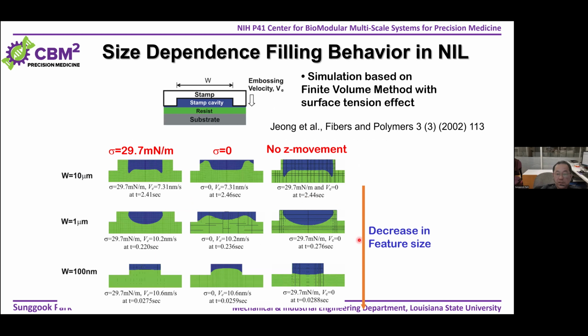And this is an older simulation result. What they want to show is how the polymer fills by squeeze flow in nanoimprint lithography depends on the surface tension as well as the size of the structures. When the size is large, the thermoplastic polymer will mostly fill first along the wall of the structures, and then fill into the gap. Once you have nanoscale features, the filling is like a plug.